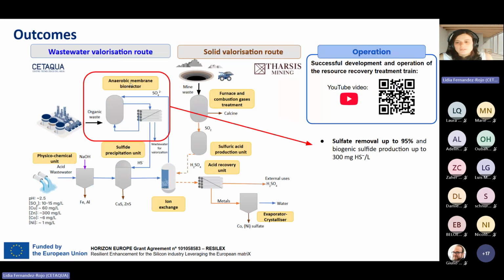The main outcomes of this treatment train were that we were able to remove up to 95% of the sulfate present in water and produce biogenic sulfide up to 300 milligrams per liter, which was used afterwards to precipitate copper and zinc and recover them for further processing. Also, we were able to produce a stream that was no longer acidic compared with the original acidic wastewater. And if this treatment train was implemented on site, there would be a 90% reduction in acidic discharge compared with the untreated mining wastewater that is there today. However, there still will need to be some other refining or polishing step before this water can be reused.